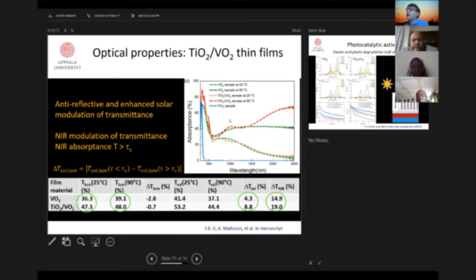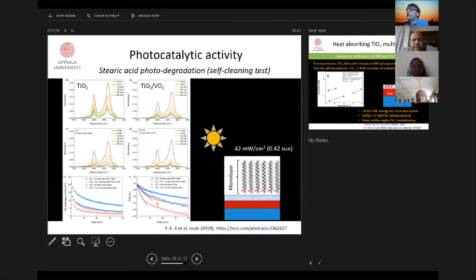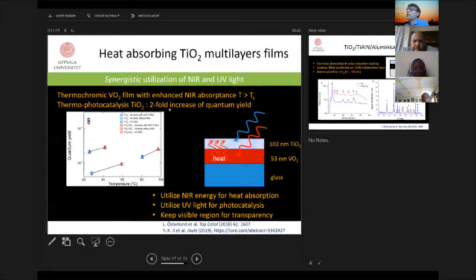And we can see it again in this bar graph structure, again appreciating the decreasing absorbance of a probe molecule as a function of time, and it decreases faster on this structure. And this is the configuration, where we are probing with a probe molecule with carboxylic end groups and solar light, and then we have faster activity. And with this concept, you can actually increase it twofold.